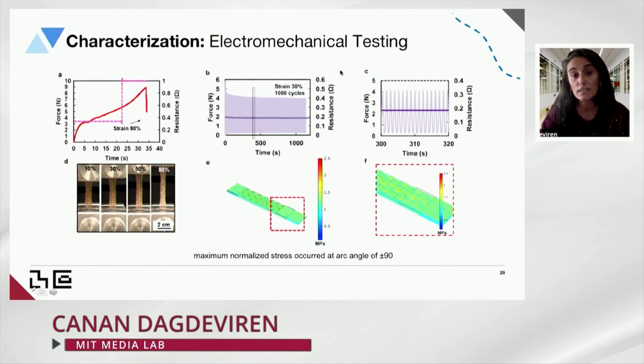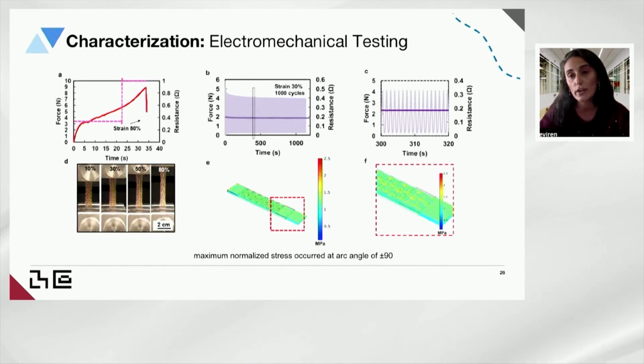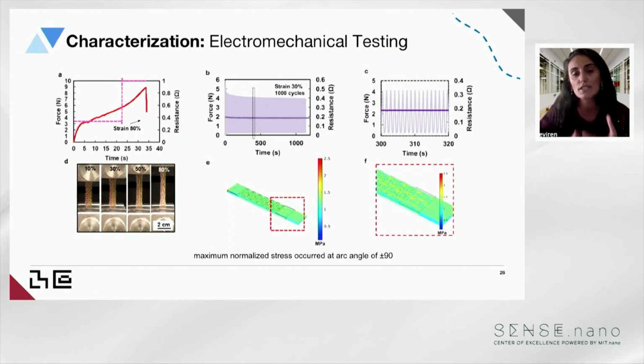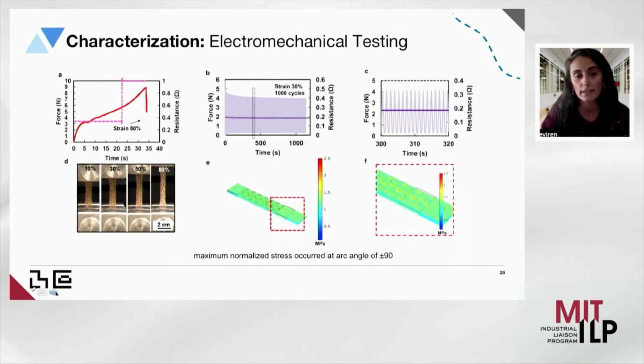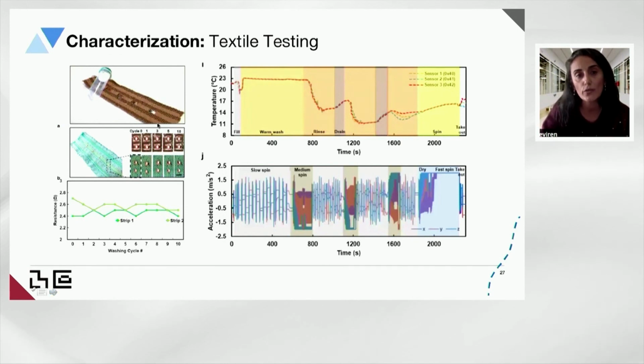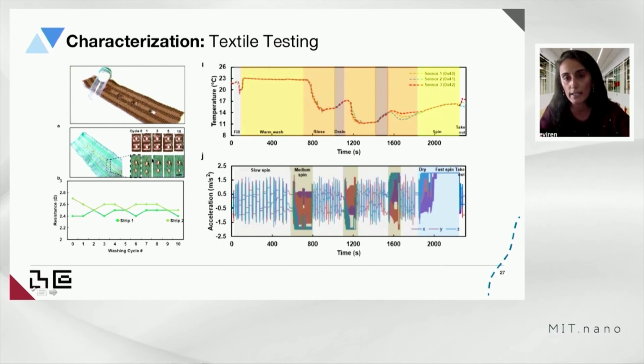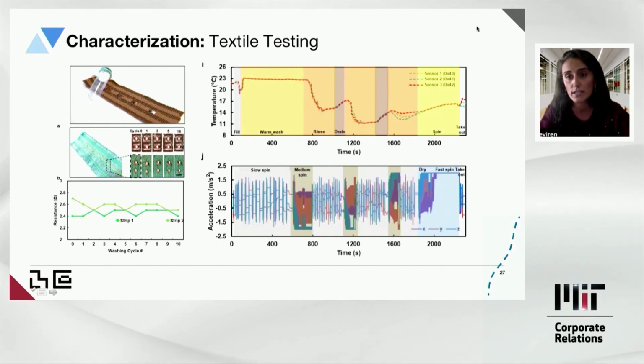Our device can be stretched up to 30% with no electrical and mechanical degradation, and under force application, the change in resistance is really tiny, which suggests that the device can be used up to thousands of cycles with no mechanical and electrical degradation, which is good because we want to use this in our daily activities. We also show the washability test of our devices, where the electronics are integrated on top of the textile, and to show that, we use an LED system and wash the system in multiple washing cycles and check the intensity of the LED to show that the electronic degradation is very negligible.